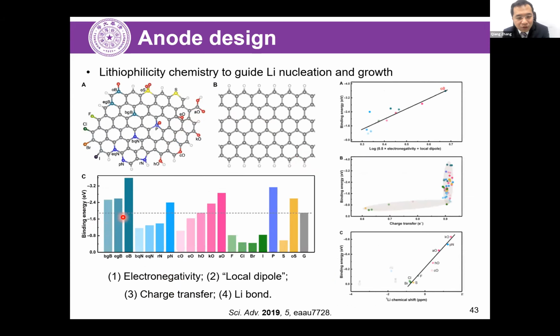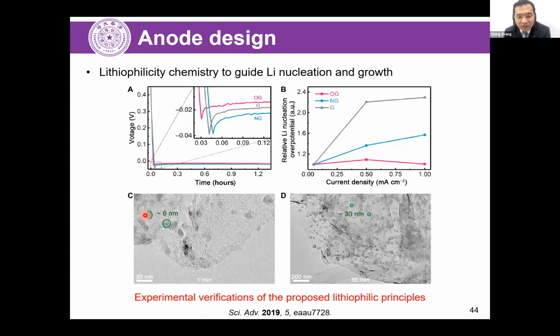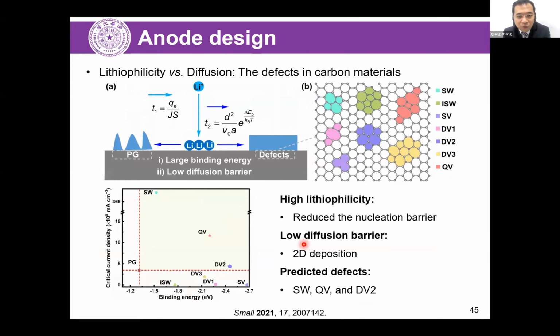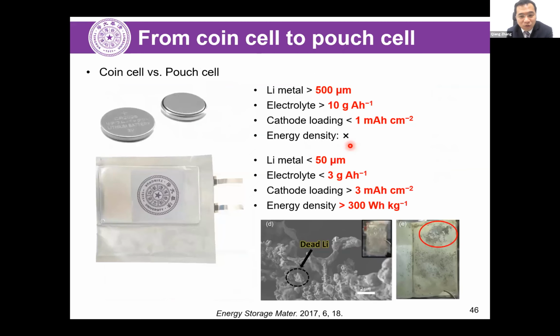And this helps the lithium nucleation be in small size and high density, and this is indeed helpful for lithium metal anode deposition into a uniform film, not lithium dendrites, in a working cell. So the lithium bond theory is quite important and necessary to guide the lithium metal anode to uniform deposition. And in the active material system, once we dope the carbon with heteroatoms, it is found that there are always several defects. The defects are not always bad. It is found that some defects, like the Stone-Wales structure, can also provide lithium bonds to the lithium ions. So in this case, it also benefits uniform deposition.